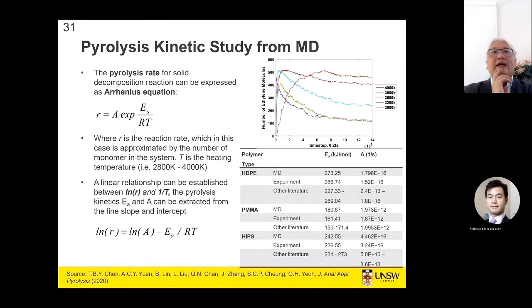So based on this, if we compare the pyrolysis kinetics, or the degradation kinetics itself, with experiments based on the Arrhenius expression, as you can see from the table here, our MD simulation really comes very close to whatever was measured during experiment, as well as other literature reported there. We are sort of in the range. So that means it gives us confidence that whatever we try to achieve is an acceptable approach. And we can now use this approach to look at a wide range of materials, especially polymeric materials that are composites in nature instead of the original polymer matrix.